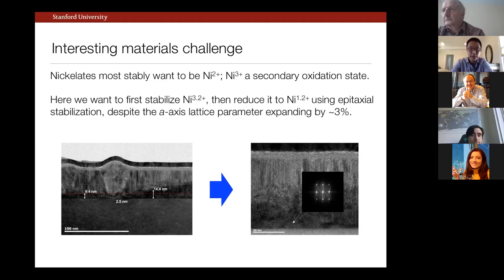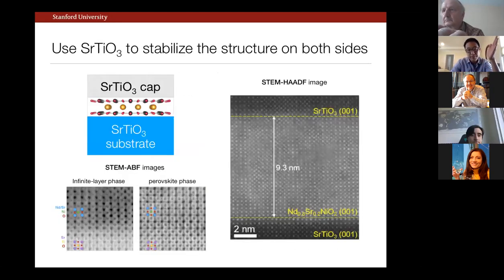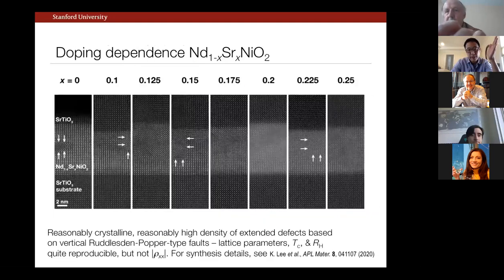Okay, I won't try to dig around quickly, but what we are finding, in fact, there was a nice paper recently that came out in Nature Communications by Beatrice Noheda, where they were only working on the perovskite phase, but they were varying different perovskite nickelates on various substrates. And what we think is going on is that, in order to accommodate the strain of our particular substrate, which is under a fairly high tensile strain, there's an intrinsic instability to make vertical Ruddlesden-Popper-like fault intergrowths. This is the way the system is trying to deal with this unhappy situation.